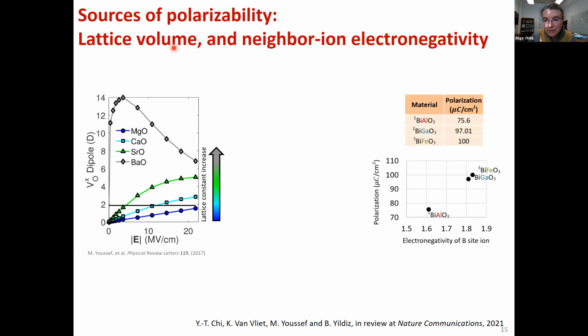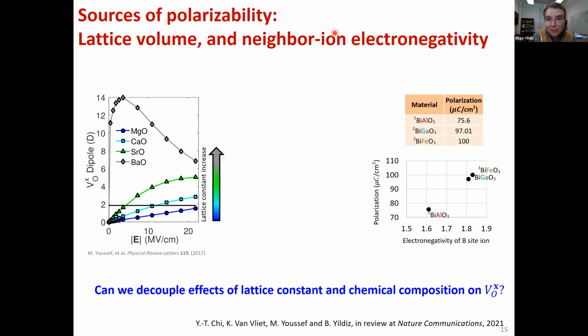And a second source that we think is important is the neighboring ion chemistry, in particular, its ability to uptake electrons that are being polarized around it. And we see evidence to this also from literature in ferroelectrics, where the ferroelectricity comes from lone pair electrons, where the polarization in polarizable materials depends on the electronegativity of the neighboring transition metal cation. Okay, so how can we resolve the lattice volume versus the electronegativity effect in the materials that we care about? And I'll go back to the strontium titanate, the perovskite system that is technologically more relevant than the simple binary oxides that we have started with.